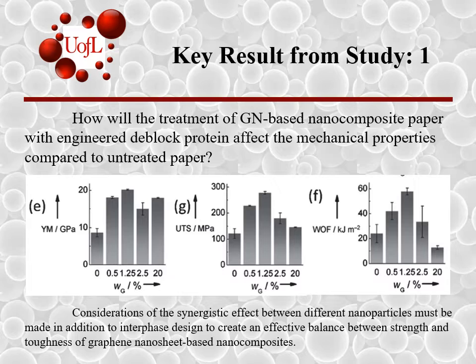The graphs below, E, G, and F, display the Young's modulus, ultimate tensile strength, and work of fracture for treated sheets of varying weight percent graphene nanosheet. We compared these results to untreated sheets, and all treated sheets showed improvement of mechanical properties and toughness mechanisms. But as the weight percent of graphene nanosheets increased for treated papers, the material indexes used didn't always show improvement. This indicated the key conclusion that considerations of the synergistic effect between different nanoparticles must be made in addition to interface design to create an effective balance between strength and toughness of graphene nanosheet-based nanocomposites.